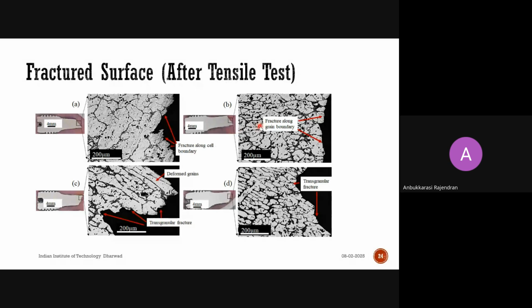We wanted to understand because one of the samples showed only 4% elongation, and another sample showed 28% elongation. Such a huge variation in the elongation we could see. The one which showed very little elongation is supposed to have failed much earlier, and must be of a brittle nature. So which one is acting as the weakest point to propagate and make a sample fail earlier? We wanted to understand that.